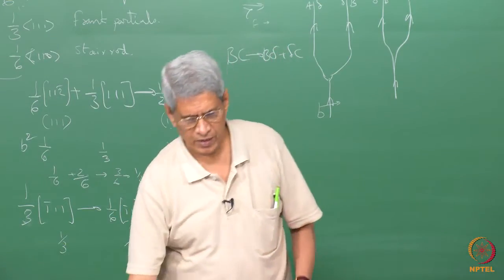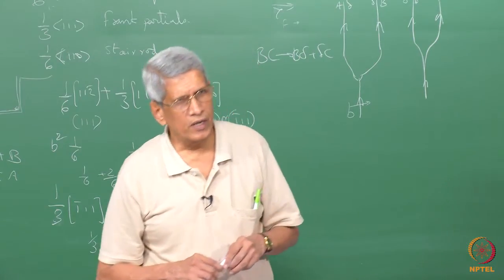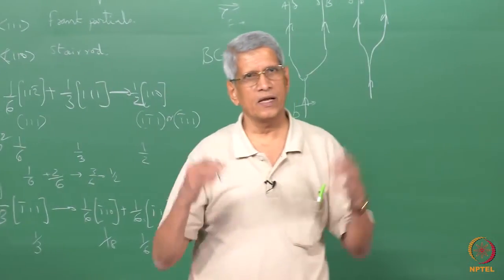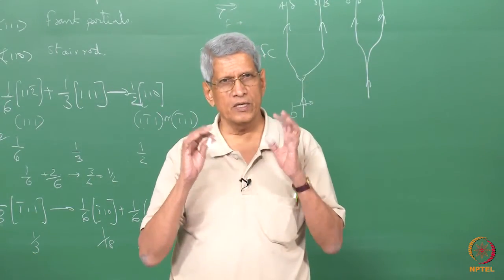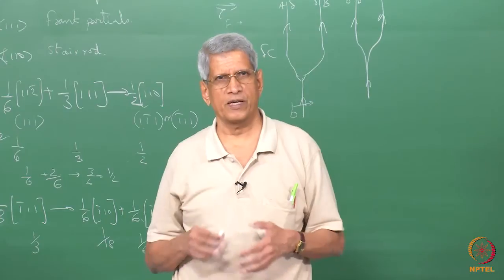In fact, if I look in this direction, assume that in the TEM I am looking at this sort of reaction which has occurred, this is the beam direction. So the projection of this is what you are going to see on the image, right? What you see in an image is a projection, but the Thompson tetrahedron gives you a 3-dimensional visualization as it appears. So that's why it's a very powerful one. And in fact, you might have noticed that in most of the books, instead of writing the Burgers vectors of the dislocations, you will always find that they write like A delta, B delta. This is the nomenclature with which it is written. The Thompson tetrahedron nomenclature is routinely used to represent different perfect or partial dislocations.